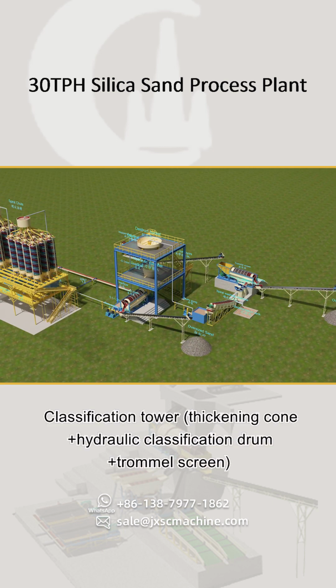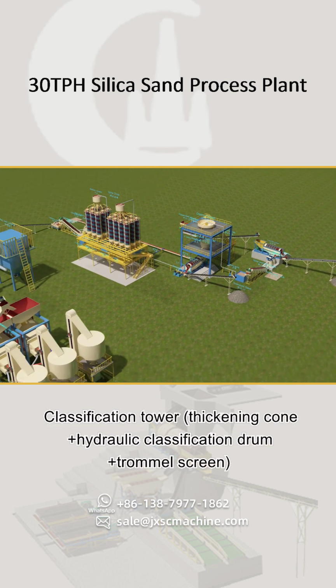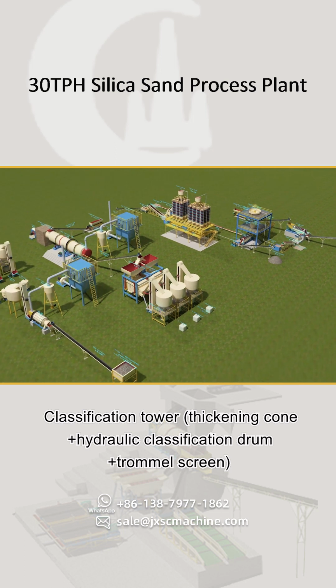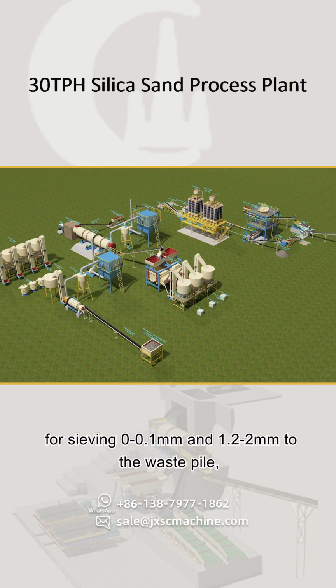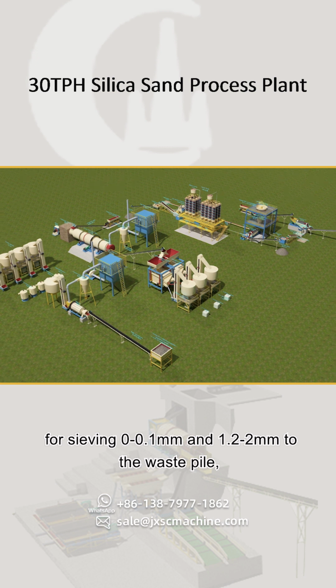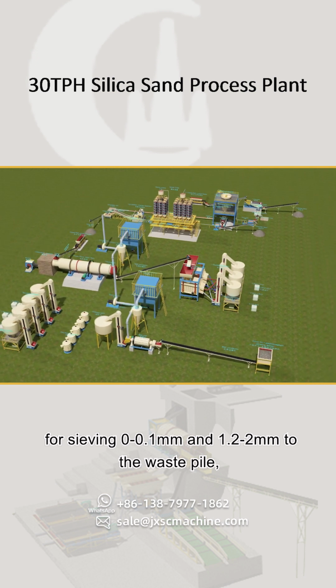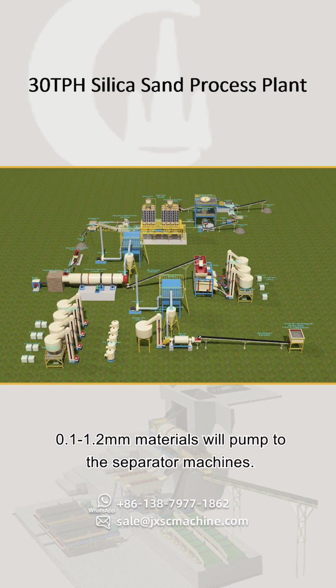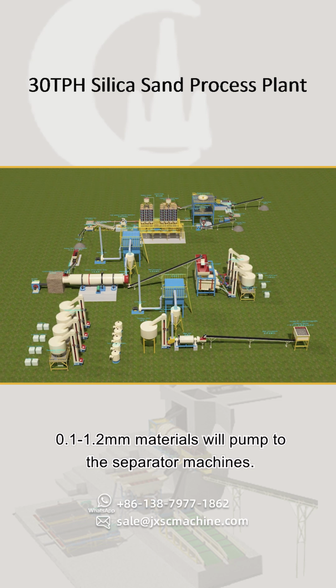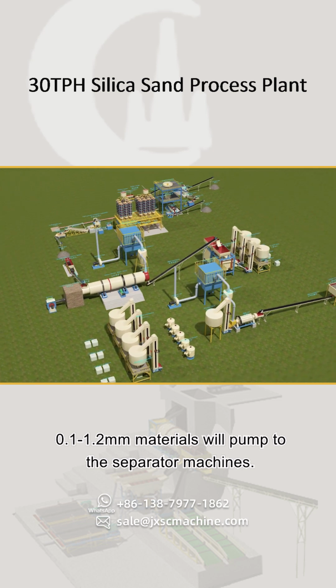2. Classification system. Classification tower: thickening cone plus hydraulic classification drum plus trommel screen for sieving. 0 to 0.1 mm and 1.2 to 2 mm go to the waste pile, 0.1 to 1.2 mm materials will be pumped to the separator machines.